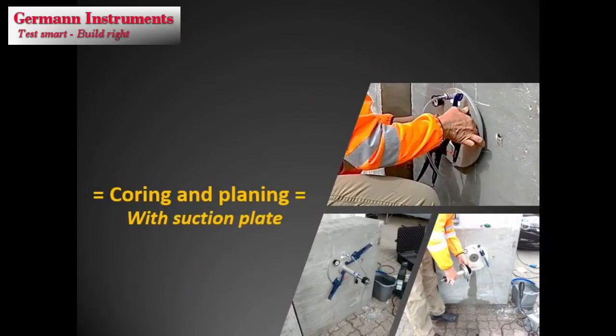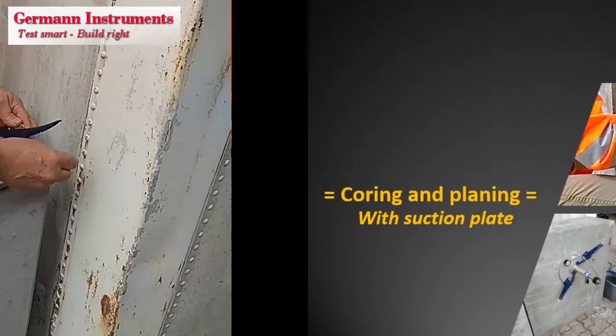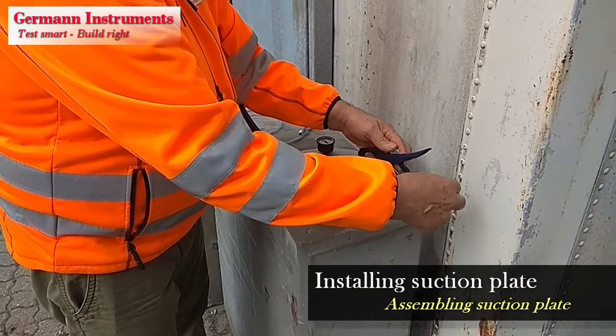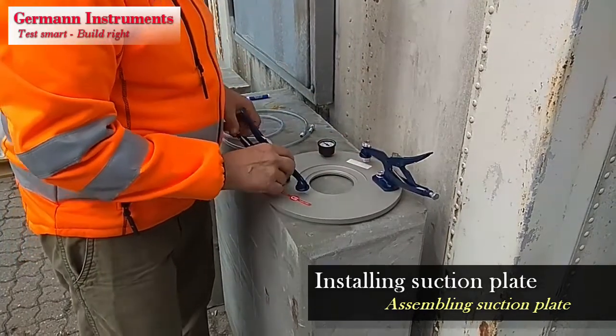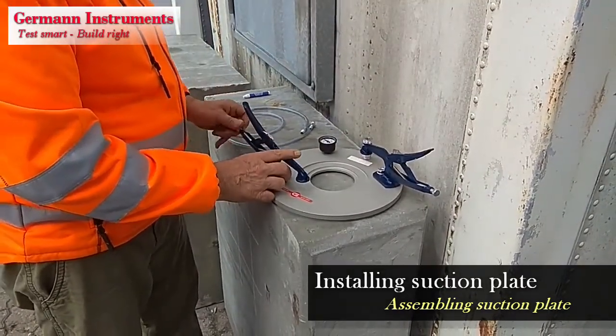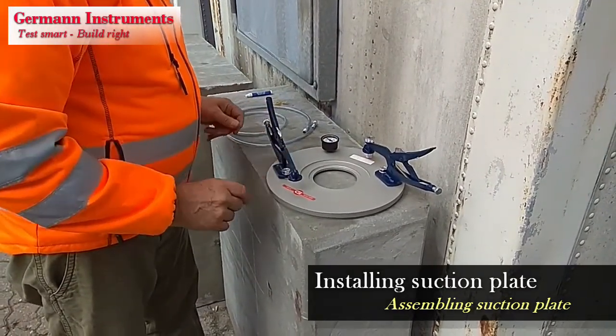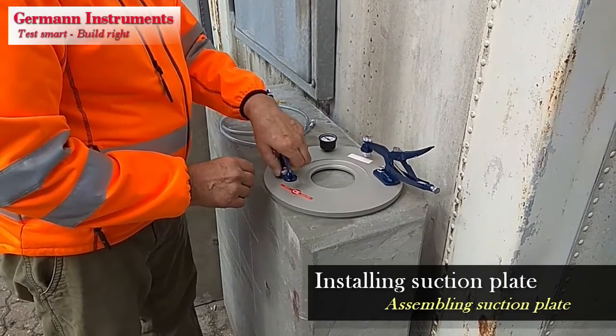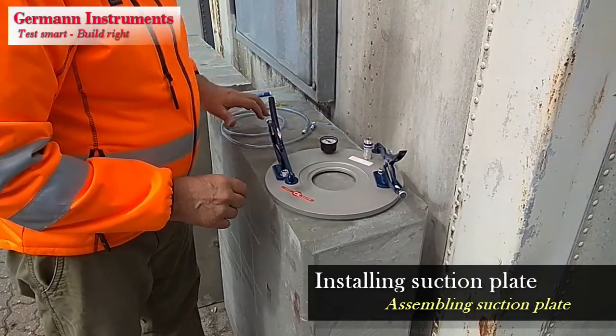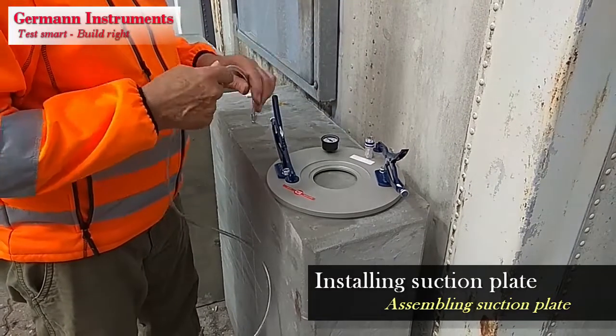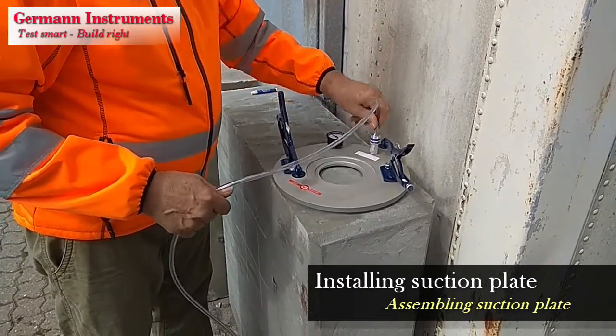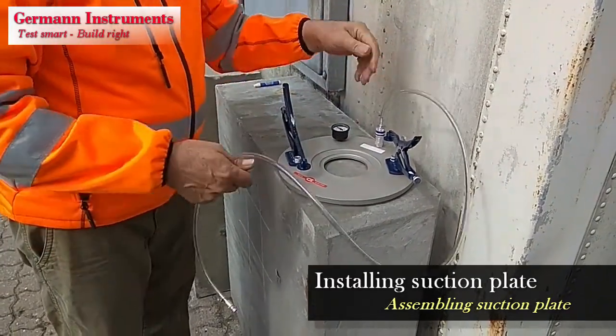The system can be used with and without a suction plate. The suction plate is recommended on even and smooth concrete surfaces. Using the suction plate controls accurately the initial 3 steps: coring of the center hole, planing of the surface and routing of the recess. Otherwise, the 3 steps are performed holding the equipment by hand, as later described.